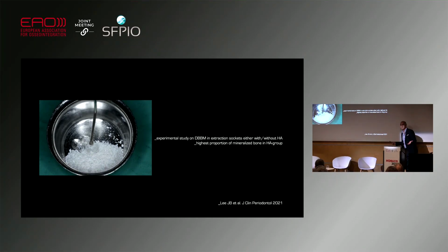And they see the same. There's more mineralized bone in the group with hyaluronic acid, which we actually 10 years ago thought was my mistake. So sometimes you understand things later, and I think today we understood that probably there's an effect of hyaluronic acid on bone remodeling and also bone mineralization.